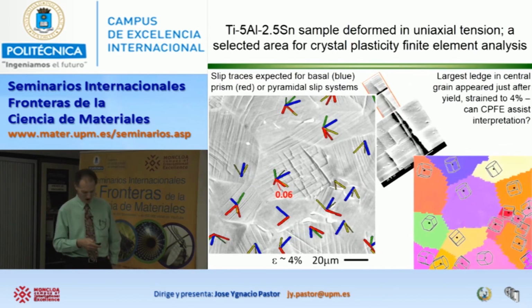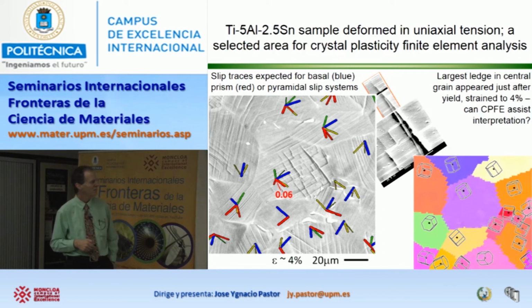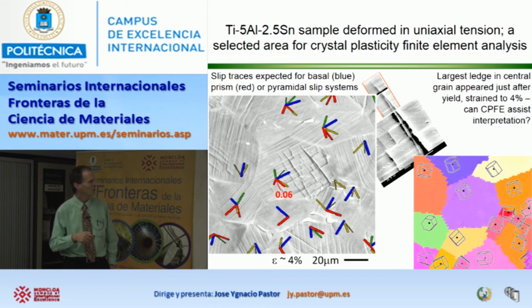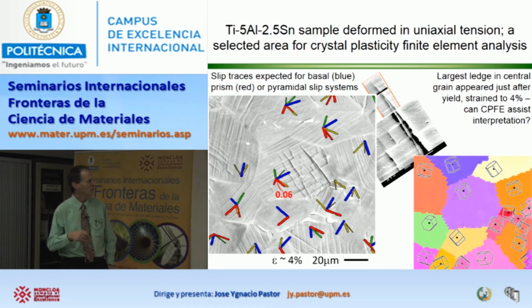So next I'll talk about some titanium. We wanted to simulate deformation in some titanium to figure out if we could understand a couple of things. One is we can clearly see slip transfer going across this boundary. The blue here represents basal slip in a hexagonal titanium, and it goes right through the grain boundary pretty well. It sort of matches up over here as well.